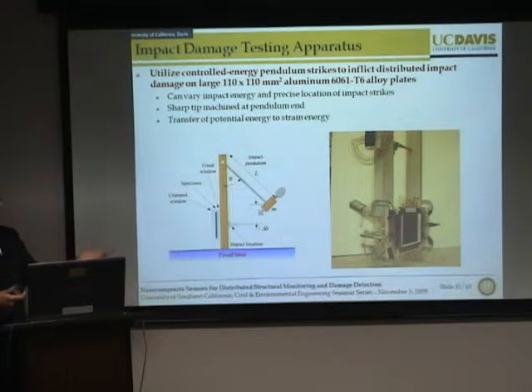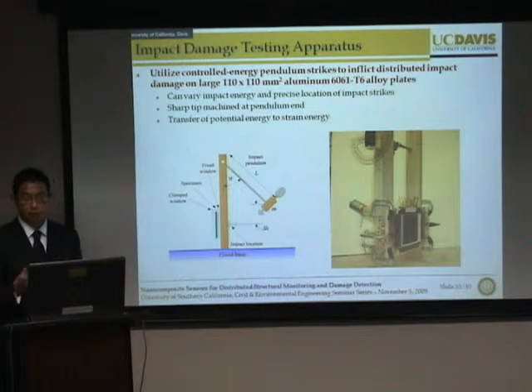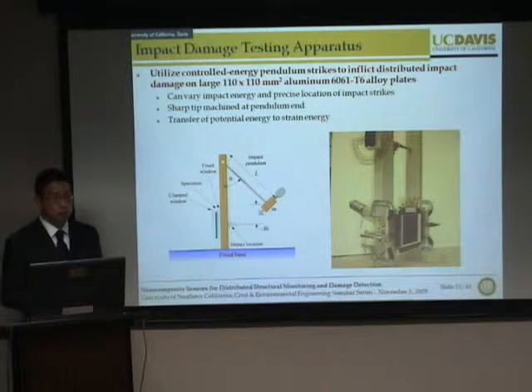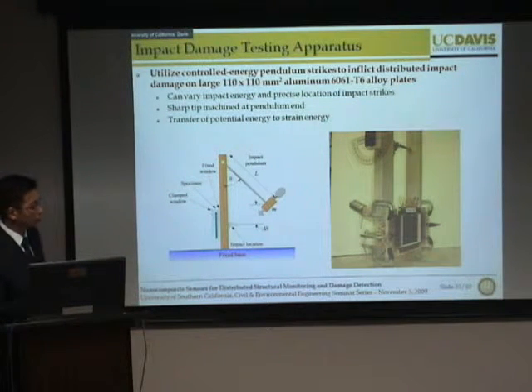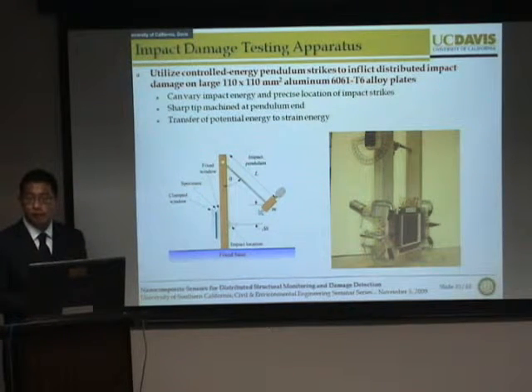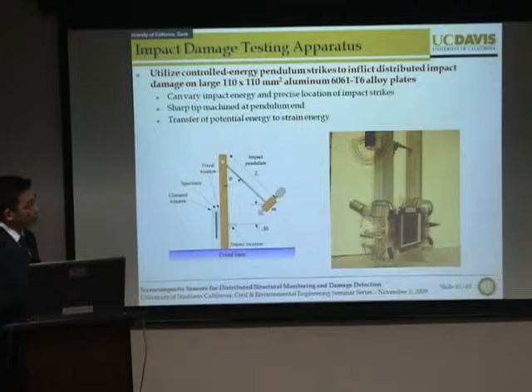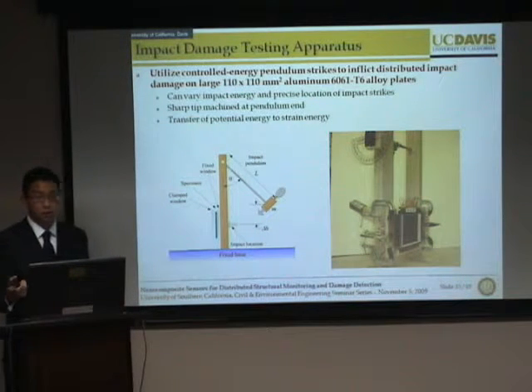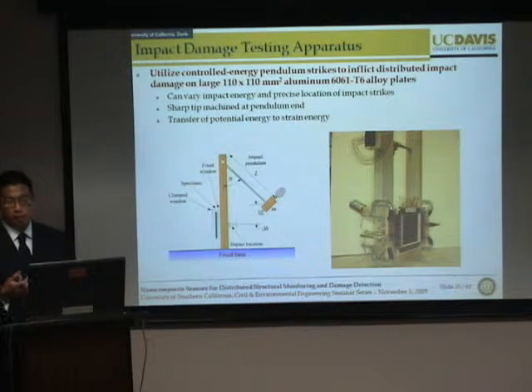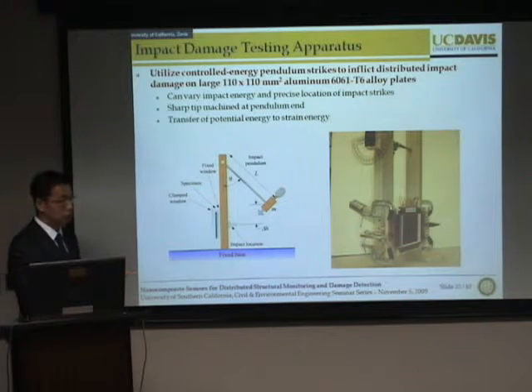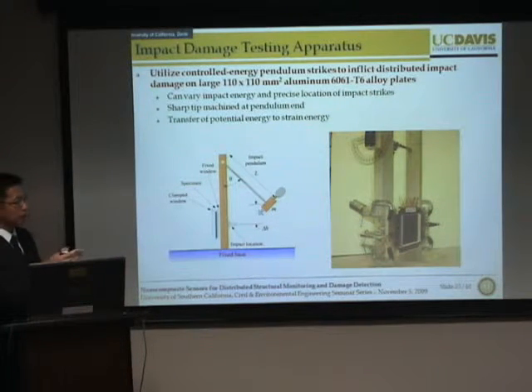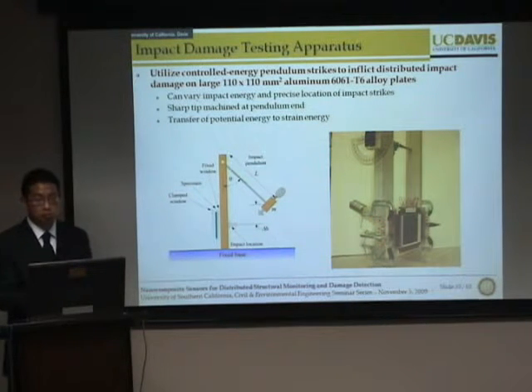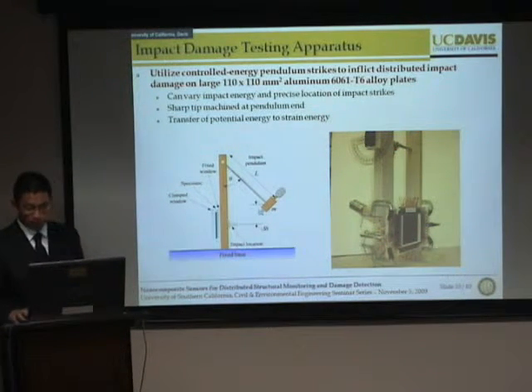So upon validating this technique for measuring changes in conductivity, our initial interest is to utilize this sensing skin approach to detect impact damage for aerospace or naval applications. Now, in order to basically perform an experimental study to see if our sensing skin can detect impact damage, we've deposited our thin film onto a 110 by 110 millimeter squared aluminum plate. We can then create this impact testing apparatus based on this pendulum structure, where we can vary the mass of the pendulum as well as the length of the pendulum in order to precisely impact our plate at different locations, as well as with different impact damage magnitudes.